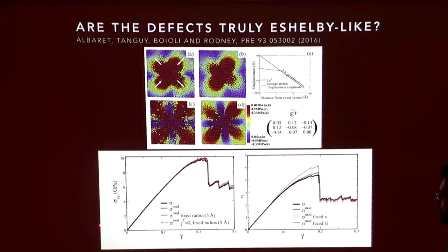So they have the stress they measured as they sheared the system, measuring stress at the boundaries of the simulation, and then the stress they've reproduced by adding up a series of Eshelby events that have a discrete effect on the stress in the system.